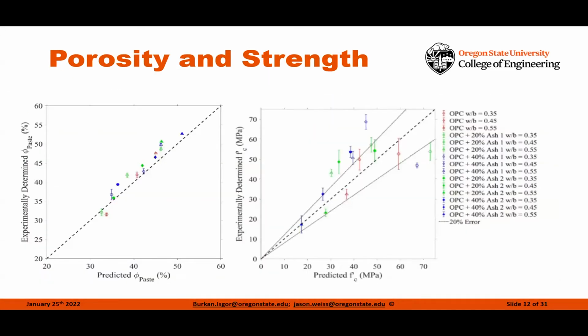Now, when we do that, we can start to compare these results. We can look at the predicted porosity of the paste in the system versus the experimentally measured porosity of the paste in the system. And if they fall along this dashed line, we simply have parity in this system, right? We have the fact that the model is predicting things well. And what you'll notice is that for the systems we're looking at here, we see a very strong correlation between the predicted porosity and the measured porosity. So porosity is probably the easiest thing for us to be measuring and predicting. And this makes sense because this is really what the model is based on.